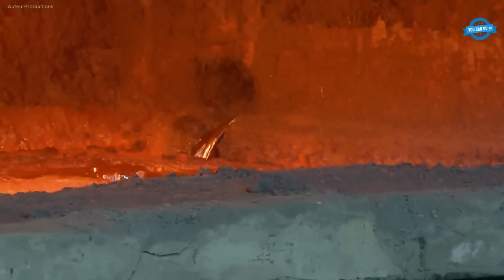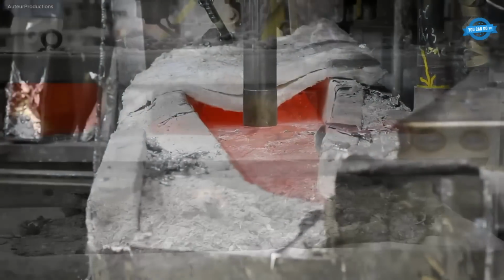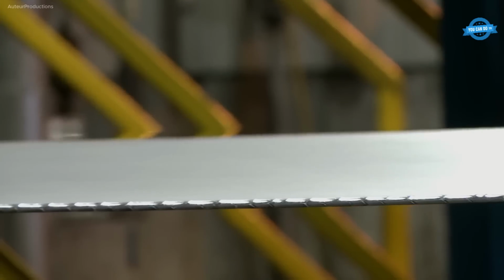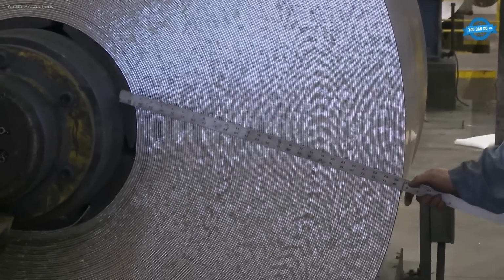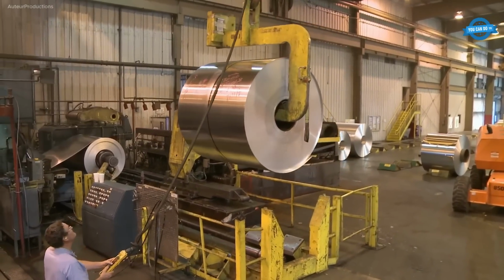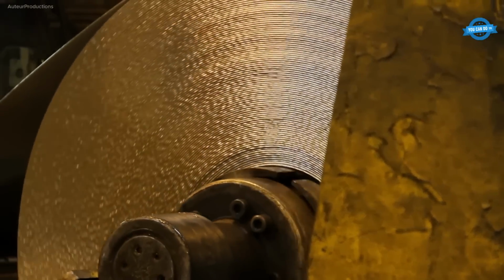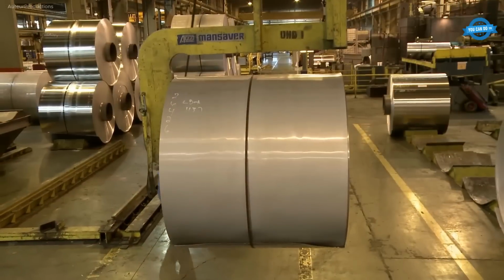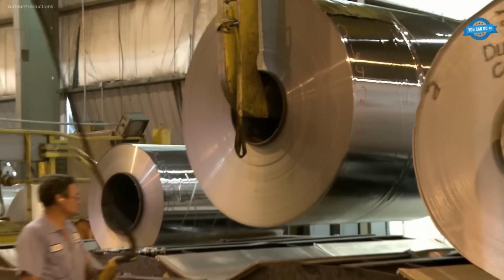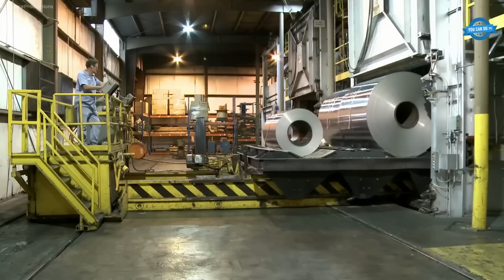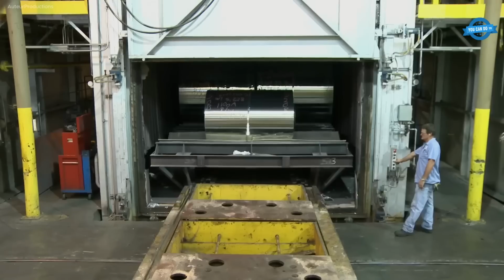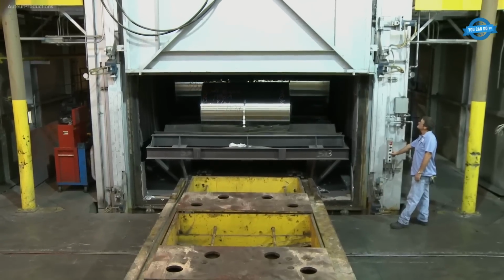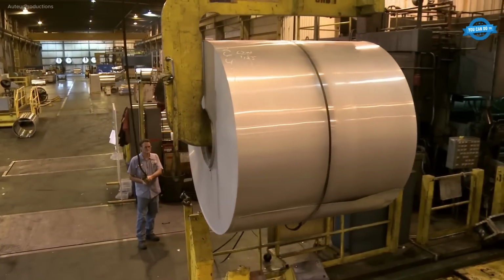Molten aluminum is transferred into casting machines through filters, solidifying into large coils via water-cooled rolls. These cast coils, once cooled, are processed in the cold mill where sheet thickness gauge is reduced. Coils are then annealed in high-temperature ovens to soften the metal, allowing for further thinning. Subsequent cold and foil mill operations reduce thickness further, with operators controlling tension, pressure, and speed to maintain product quality and prevent defects.